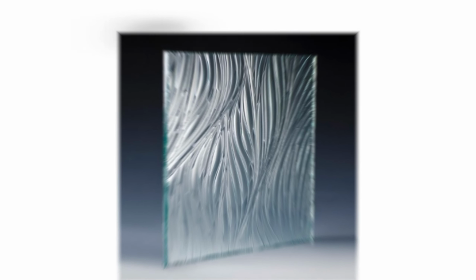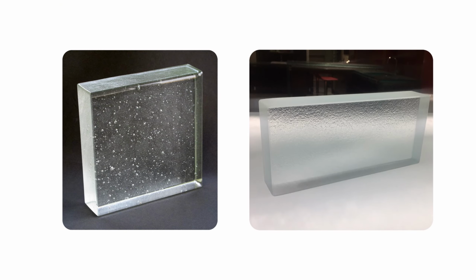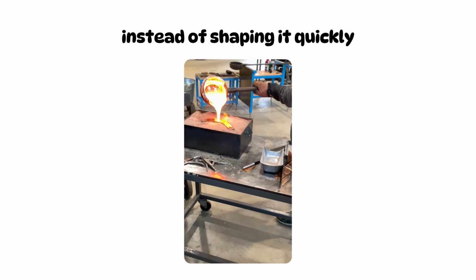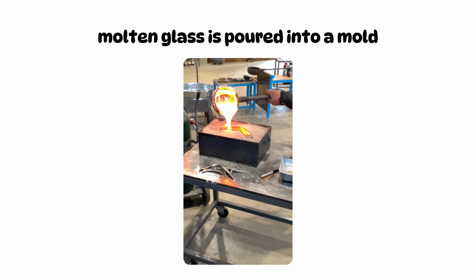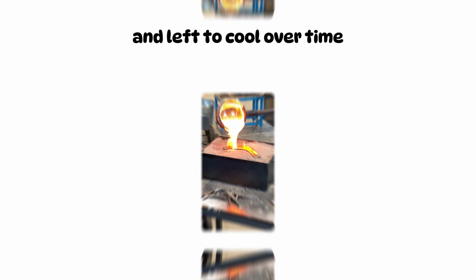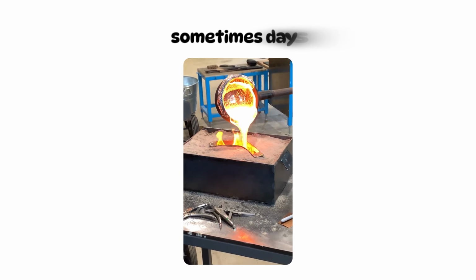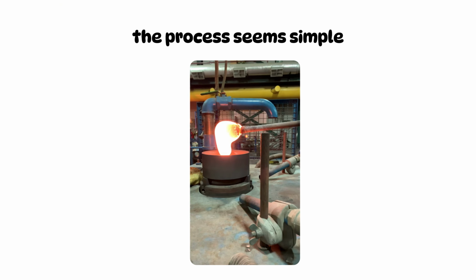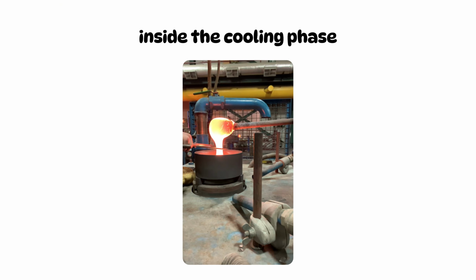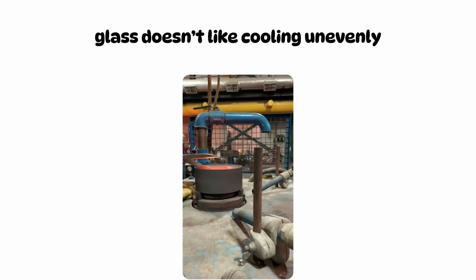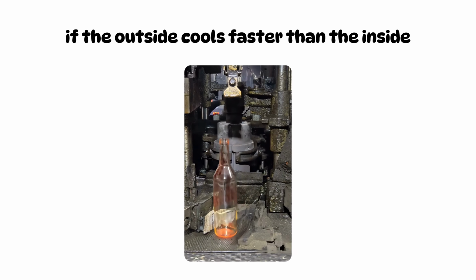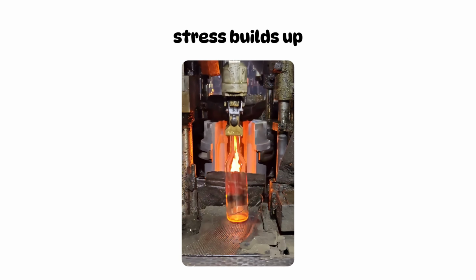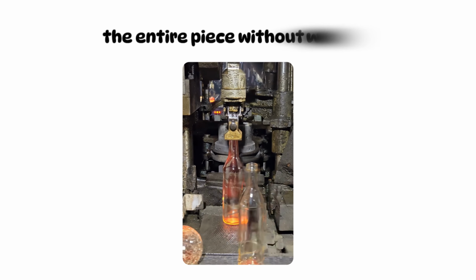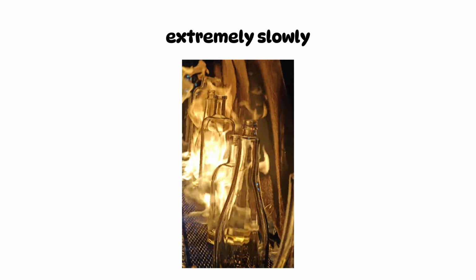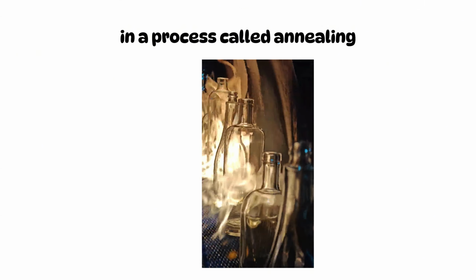Cast glass. This is the heaviest and slowest way to make glass. Instead of shaping it quickly, molten glass is poured into a mold and left to cool over time, sometimes hours, sometimes days. The process seems simple, but the danger is hidden inside the cooling phase. Glass doesn't like cooling unevenly. If the outside cools faster than the inside, stress builds up, and that stress can crack the entire piece without warning.